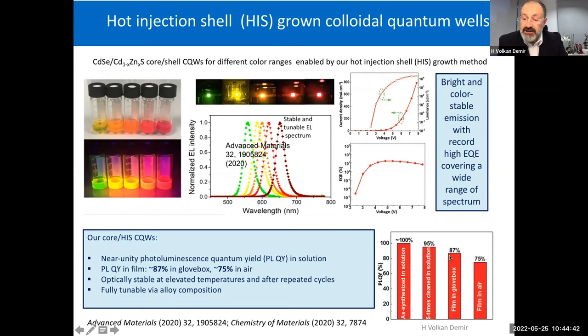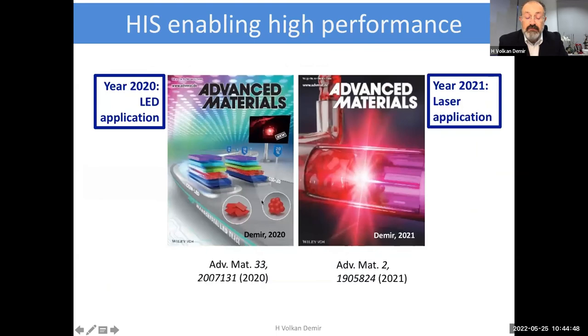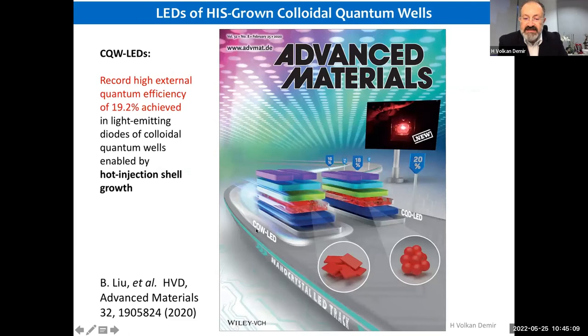So this material system, within the last 2 years, enabled us to push the performance limits and break two records in two different aspects. One is LED fabrication, and another one is in solution laser application. So what we found is using this type of highly engineered colloidal quantum wells, we can actually put their electrically driven LEDs on par with any other best efficiency soft material devices. This is 19% efficiency achieved. And this is in itself a performance limit.